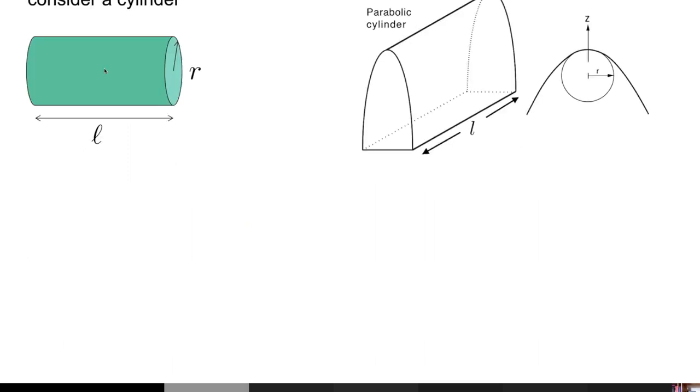And that something is to do with the curvature of the interface, okay? Curvature itself changes equilibrium at the interface. So if you think about a cylinder, this is the shape of a Widmanstätten ferrite. It's what we call a parabolic cylinder. So you take a parabola and you extend it along this direction with the distance L here.